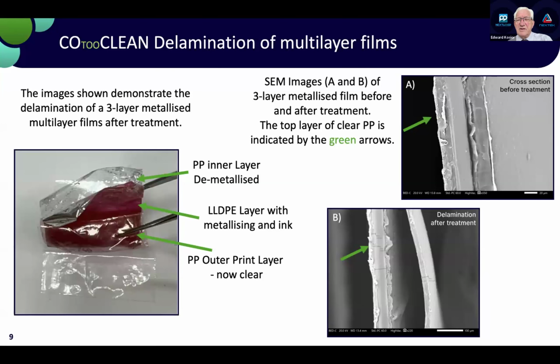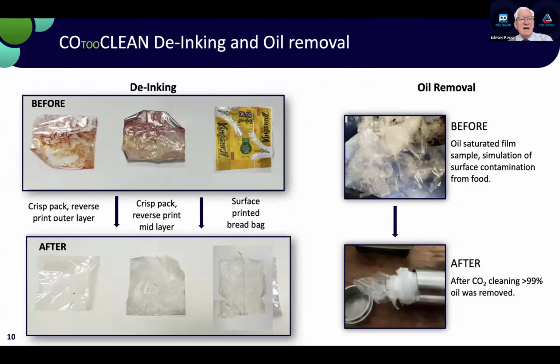We know that multi-layer materials are being replaced by mono materials, but we still have quite a lot of metallized and multi-layer materials put on the market. So potentially this process could be used to deal with some of that complexity. On the de-inking side, here we're using printed films. The first 2 examples are from the crisp packets, and by using a co-solvent with the CO2 in the supercritical state, we can remove the inks. And also on the right-hand side, we've created oily films where we've just simply soaked the films in oil, and we can remove those oils again in the process. So these are quite important steps in the recovery of films, because many films are both printed and oily.